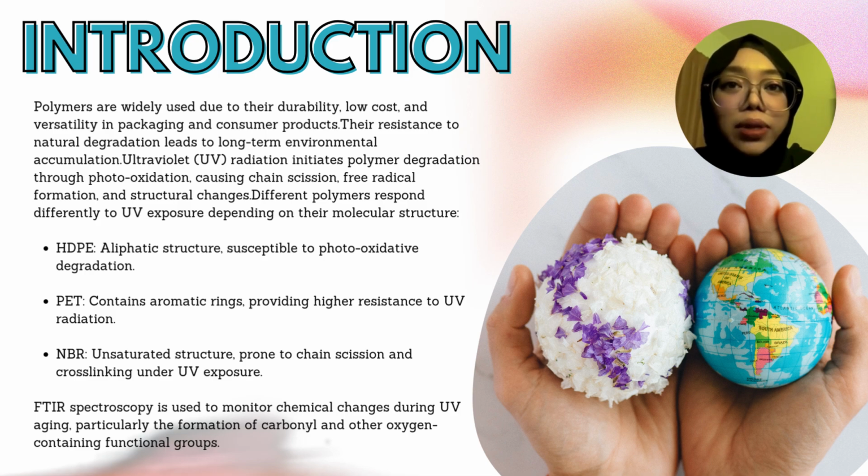HDPE has a simple aliphatic backbone and is more susceptible to photooxidative degradation. PET contains aromatic rings which provide better UV stability. In contrast, NBR has unsaturated bonds that are more sensitive to UV exposure, leading to chain scission and cross-linking.